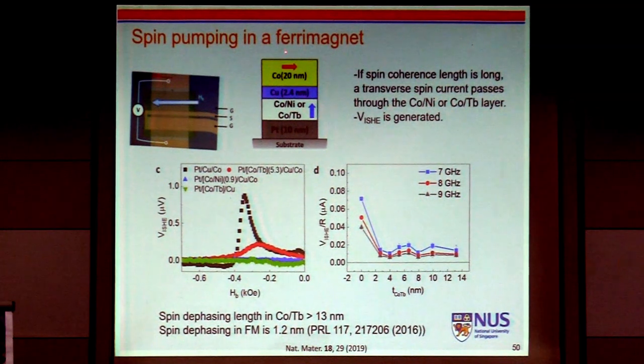It's spin pumping into a ferrimagnet to prove this material indeed has a long spin coherence length. So we injected in-plane spin, and we put a copper layer to decouple this layer. Then we have a cobalt nickel or cobalt terbium layer. Cobalt nickel is a ferromagnetic phase, and cobalt terbium is a ferrimagnetic phase. Then once we put a 0.9 nanometer cobalt nickel perpendicular layer, basically the spin pumping signal is zero.